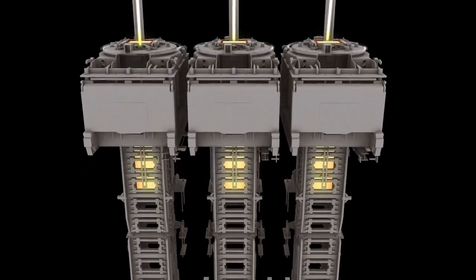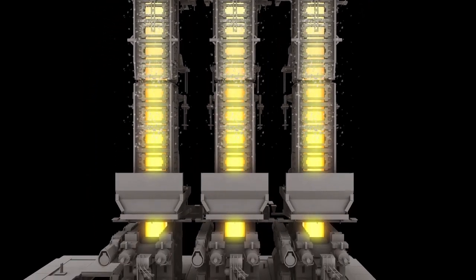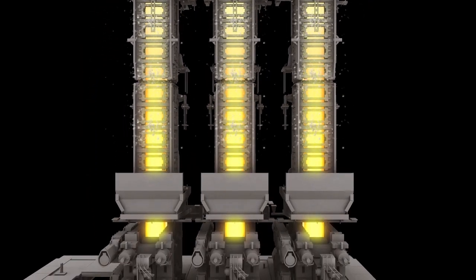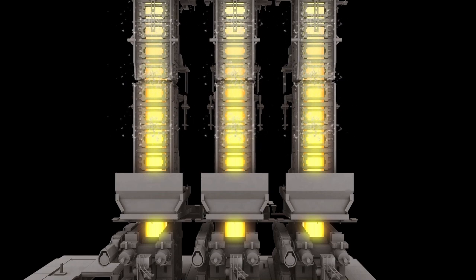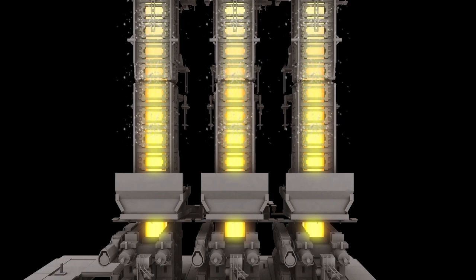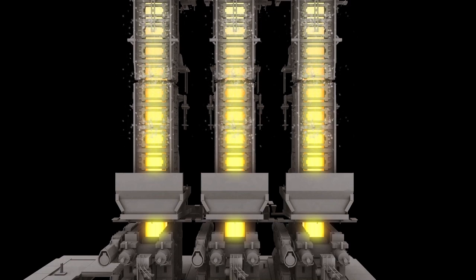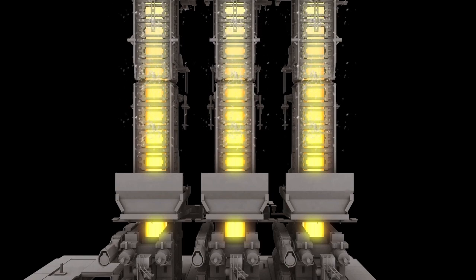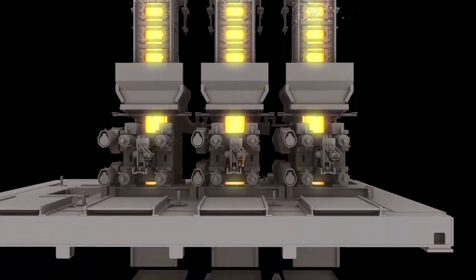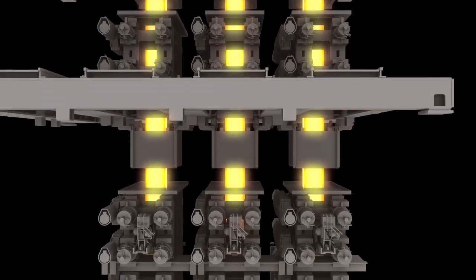Below the mold, the cast steel descends vertically with support from a series of rolls contained with 2 segments. These rolls prevent bulging of the bloom surface. Between the rolls, we use air mist sprays to cool the bloom surface and strengthen the solid steel shell. Below the segments, a series of large rolls support the strand.